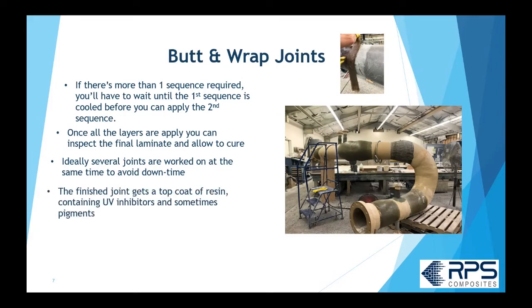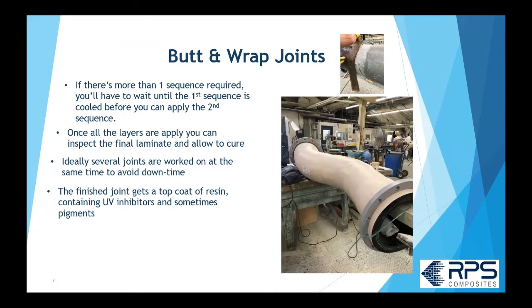And then once all the joints are done, you're going to put a top coat over the laminate that has a UV inhibitor, sometimes pigments, and you get a final product like this, where you just see kind of that hump in the middle where the butt joint is, the seam between the two pieces of piping or the pipe and fitting. And generally speaking, you'd wait about 24 hours before you'd put the finished joint into service.